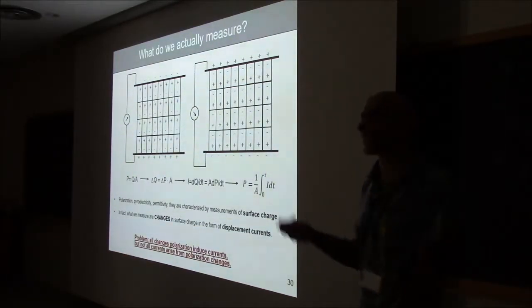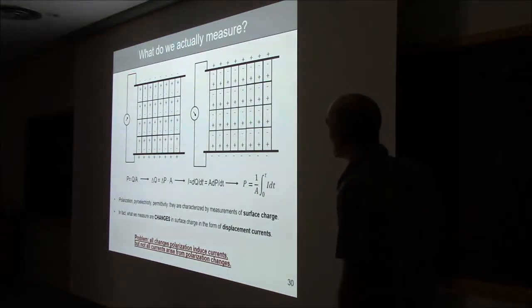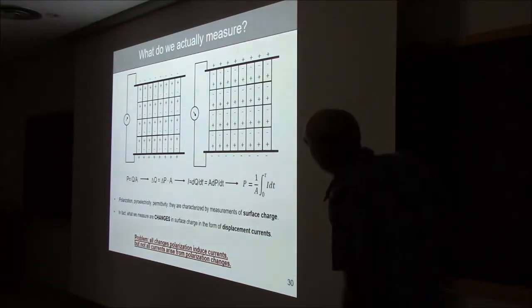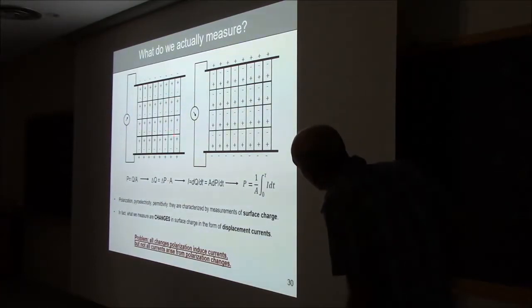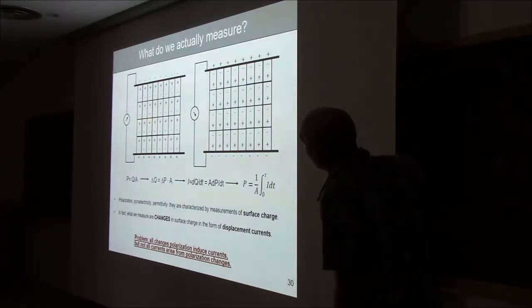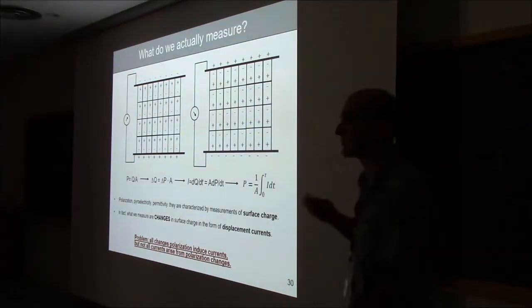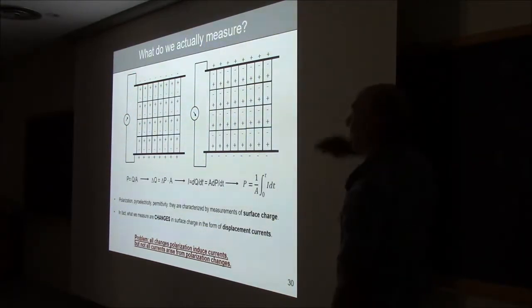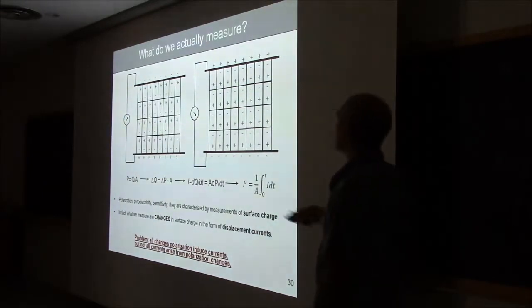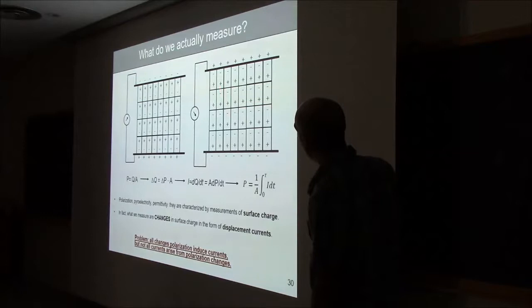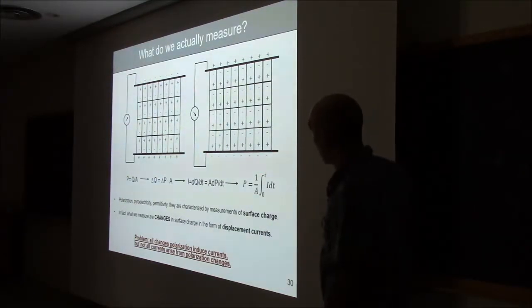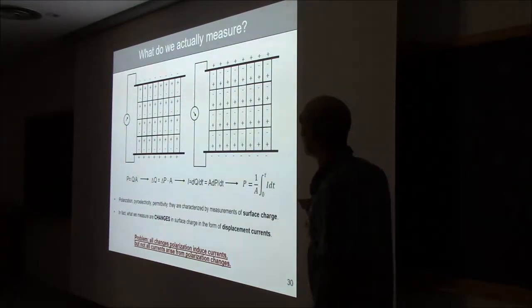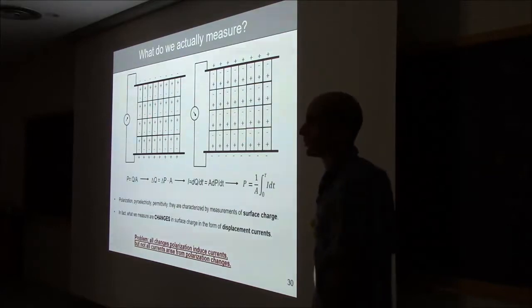And the way it works is like this. You have your ferroelectric with your electrodes, okay? Remember, if you have your polarization pointing up, you have some negative screening charge here, some positive screening charge here. Fine, that's stable. If I apply a voltage and I switch the polarization from being up to being down, then now the screening charge that I need here has to be positive, and the screening charge that I need here needs to be negative. If I have an ammeter connecting these 2 things, I can measure the flow of charge going from here to here, when you go from this situation to this situation.